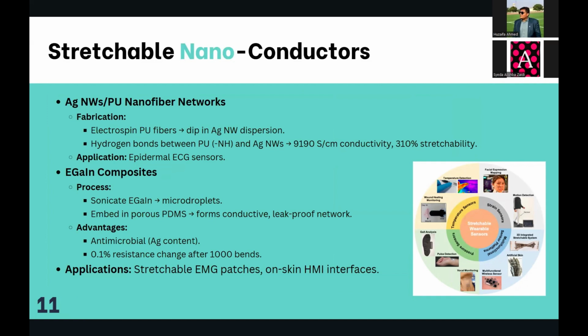Stretchable nanoconductors, which are silver nanowires and PU networks. PU is basically polyurethane. The fabrication is done via electrospinning PU nanofibers and then dipping them into silver nanowires dispersion. Then hydrogen bonds form between the PU's amine group and the silver nanowire, creating a mesh with 9190 S/cm conductivity and 310% stretchability. The application for this is these networks power epidermal ECG sensors that stay functional even during intense workout.